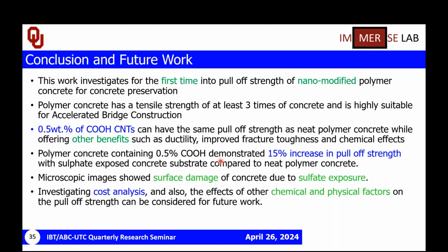And also, the polymer concrete containing 0.5% COOH demonstrated a 15% increase in pull-off strength when we have the unhealthy substrate, or the substrate which was exposed to the sulphate environment. And as I mentioned earlier in the microscopic images, you can see the surface damage of the concrete due to the sulphate exposure. And for future work, you can investigate the cost analysis and the effects of other chemical and physical factors on the pull-off strengths of these materials.